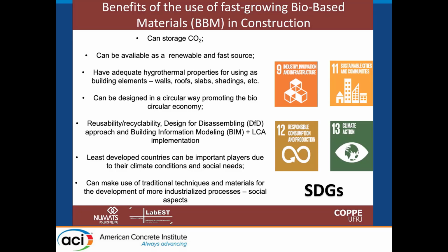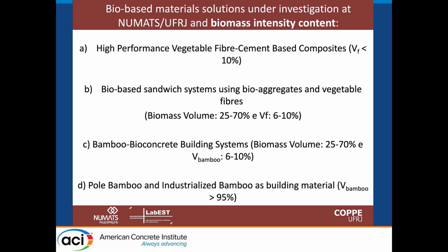So I would like to show you here, I made a division based on the volume of natural vegetable fiber that we put in the composites. I could classify in 4 levels. When we use the fibers as normal reinforcement or textile, we normally have less than 10% in volume in the composition of the materials. But we can go to nearly 95% when we have bamboo pulp or bamboo industrialized as the main constituent. In this case, we can have up to 95% of biomass. And this is very important because the biogenic carbon can play a big role, and we can be even negative in emission if we use this material.